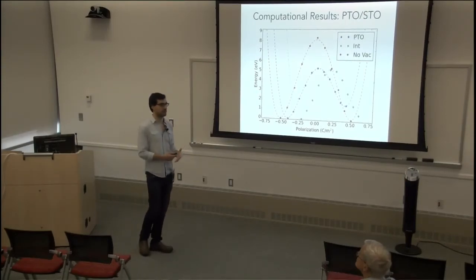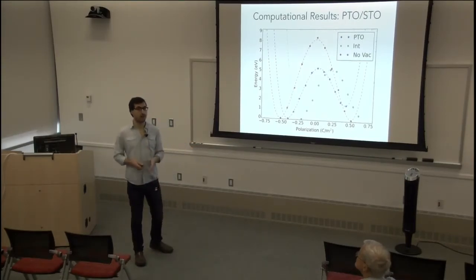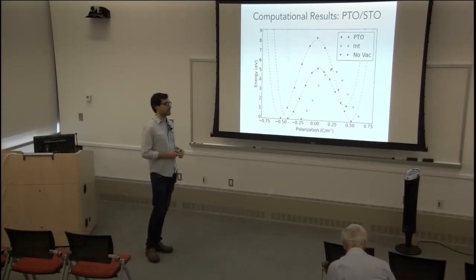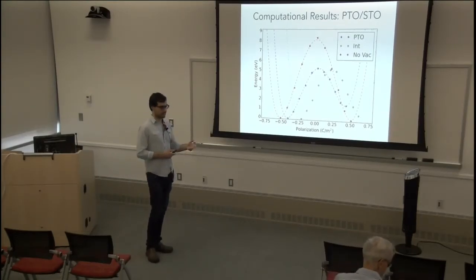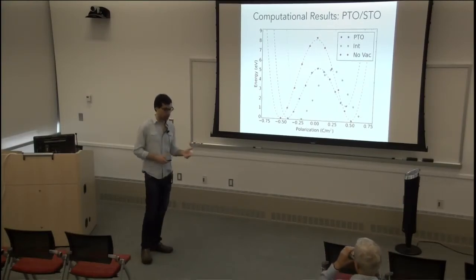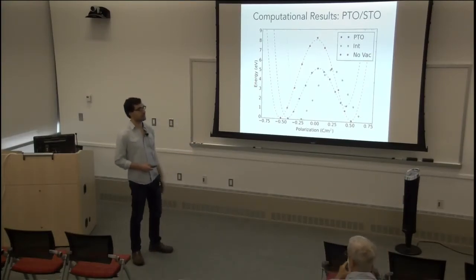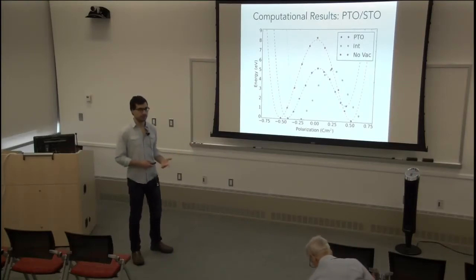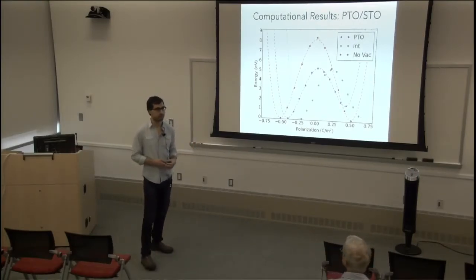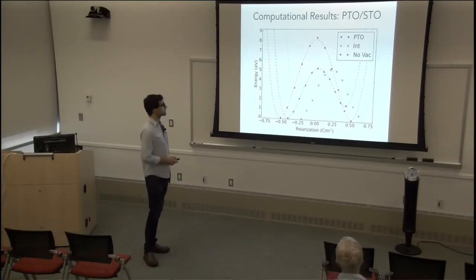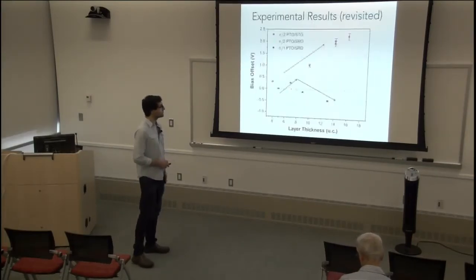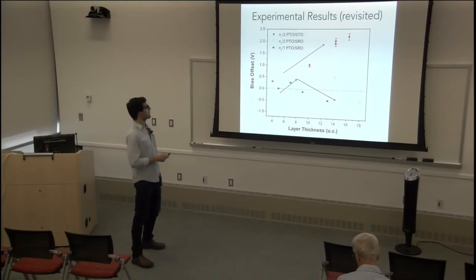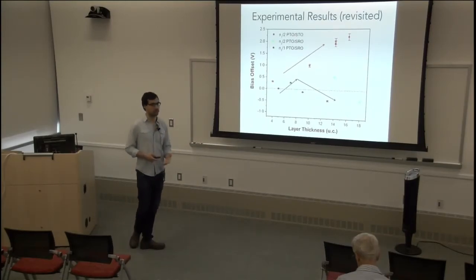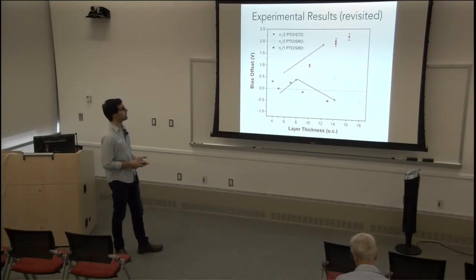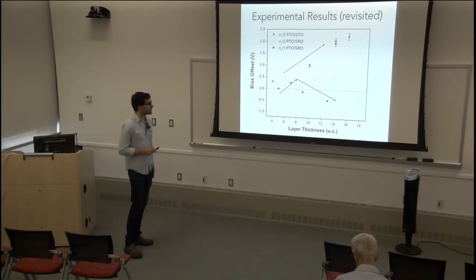So we have indirect measurements that show that oxygen vacancies are responsible for this bias, but we cannot see, okay, look, this is a picture of a oxygen vacancy using an electron microscope. But there are indirect ways to show that oxygen vacancies are responsible for this, or at least a big chunk of the bias that's being observed.